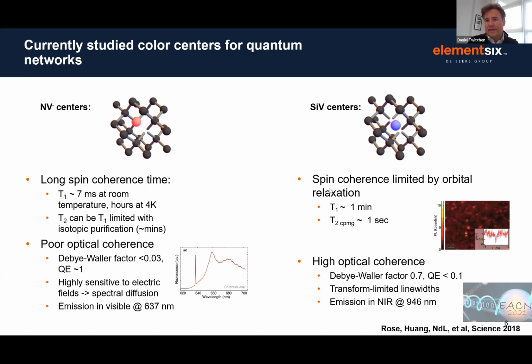That can be a challenge when you want efficient coupling of photons away from these spins in the material. The silicon vacancy has been explored in the last couple of years by a number of groups, and Jorg talked about some of that, and there is some lovely work from Natalie in Princeton, Leon in Princeton, and the Harvard teams. That's increasingly leveraging the neutral charge state of the silicon vacancy defect. It's a defect that hadn't been explored that much until the last 4 or 5 years. One of the nice things about it is it emits at 950 nm, in the near infrared, much closer to the telecoms wavelengths. Again, while you have to resort to cryogenic temperatures, in this case it can have very long T1 and T2 times, with the benefit of better optical properties. Not only is the emission in the NIR, it's also a much narrower transition. So that's one of the reasons why it's being explored at the moment.